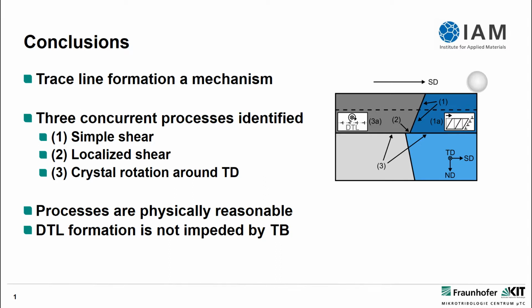When we look at the ACOM data, they seem to make sense. And the dislocation trace line formation, that's also an interesting result. It's not impeded by the twin boundary, it really just seems to go through it. That's also something we have seen when looking at specific grain boundaries.